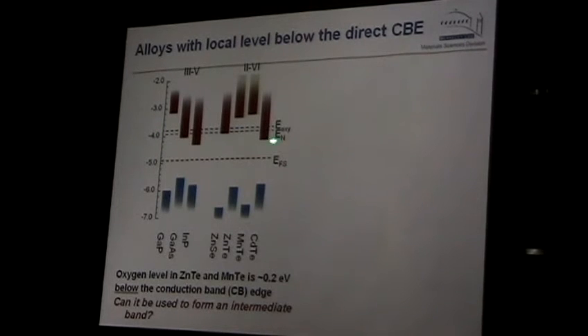In this case, of course, we can introduce oxygen. The oxygen level, we know, in gallium arsenide was slightly above the conduction band edge. However, if you go towards gallium phosphide, if you change the composition of gallium arsenide phosphide this way, then you could get material with the oxygen level inside the gap. The same is true about zinc telluride. When we put oxygen in zinc selenide, we knew it was again in the conduction band. However, zinc telluride has a conduction band much higher, electron affinity smaller. Then the oxygen level comes down and is below the conduction band edge.